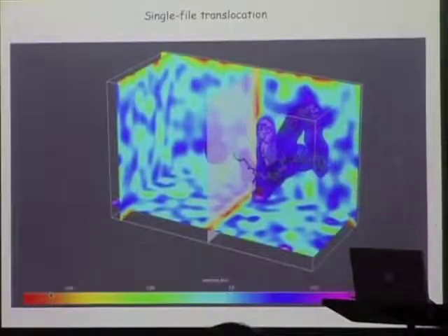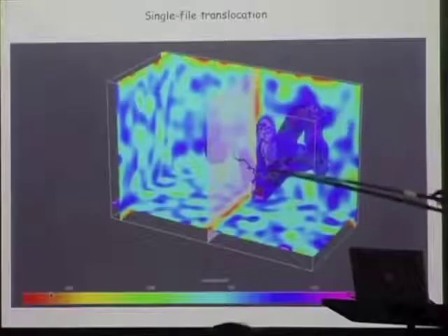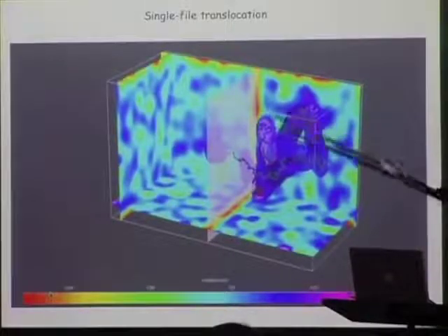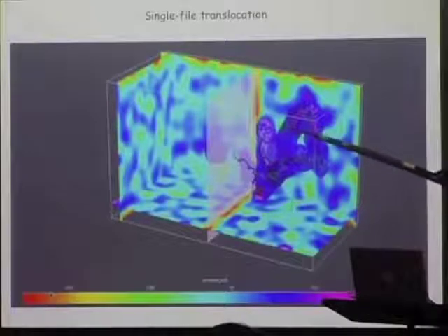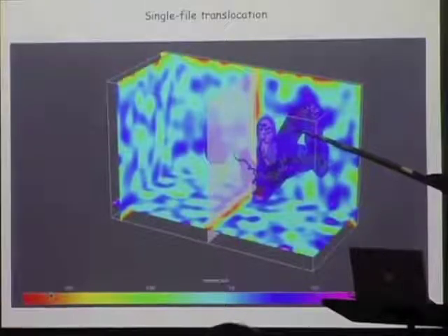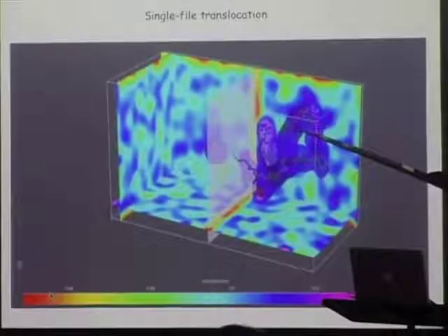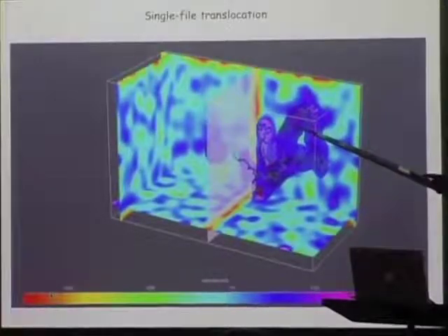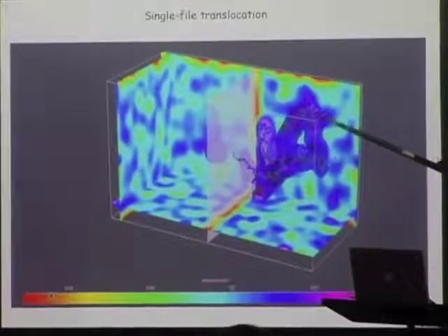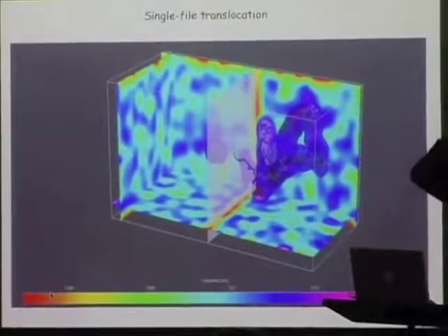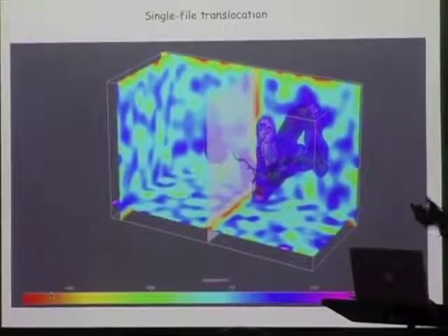So that's a typical picture of what we do. Here you see the chain getting through the hole. And one nice thing you can do in the simulation is plot the so-called synergy. The synergy is the amount of work that the fluid is putting on the polymer. So you take the fluid speed, scalar product with the molecular speed, which gives an idea of how much work you are putting into the polymer, and we plot the isocontour of this synergy. It is interesting to notice that this synergy is basically frozen into the material polymer. In other words, you define a sort of effective polymer, which is the material polymer surrounded by its synergy, which is the amount of cooperation that it gets from the solvent.